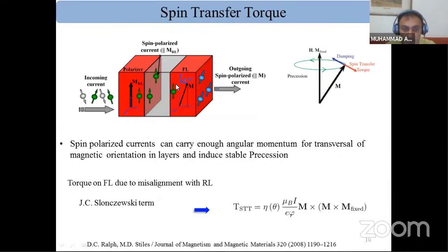Now about spin transfer torque, spin polarized current can carry enough angular momentum for reversal of this free layer. The spin transfer torque arises due to the misalignment of a free layer with respect to a hard reference layer. This you can see here. This is the magnetization of the free layer with a cross product of the magnetization of the fixed layer. We can observe from this that spin transfer torque is only observed when we have a non-collinear system. That is, spin transfer torque is observed when the angle between the free magnetization and fixed magnetization is not equal to 0 or 180 degrees.